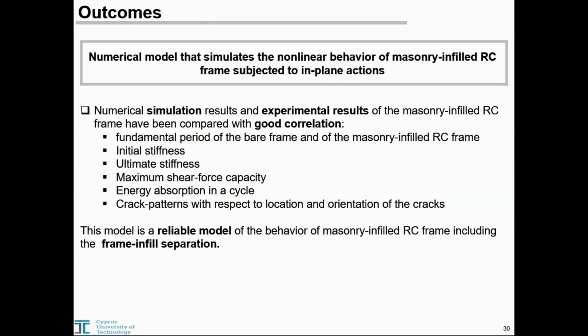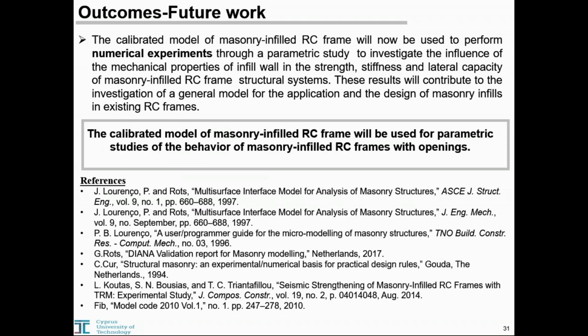The numerical model could simulate the in-plane nonlinear behavior of a Masonry-infilled RC frame with good accuracy in terms of fundamental period, initial stiffness, ultimate stiffness, maximum shear force capacity, energy, crack patterns with respect to the location and orientation. In addition, the gap opening between infill wall and RC frame, the numerical model, and the experiment has been compared and presented an analytical correlation. In particular, the energy and the maximum shear capacity in the last cycle of loading is overestimated compared to the experimental results, which may be attributed to high nonlinearities at that stage during the experiment.